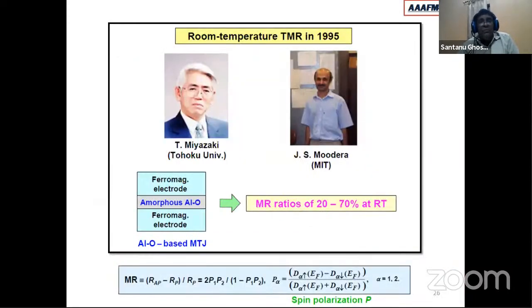And in 1995, Professor Miyazaki and Professor Moodera showed another kind of magnetoresistance effect, which is called tunneling magnetoresistance. In tunneling magnetoresistance, there are basically two ferromagnetic electrodes. In between, there is an amorphous oxide layer, and one can achieve 20 to 70% TMR in this material. Of course, after that, there was a lot of work, and people have shown very high enhancement of TMR. And this is basically the density of states variation near the Fermi level of up and down spins, which is the basic physics behind that.